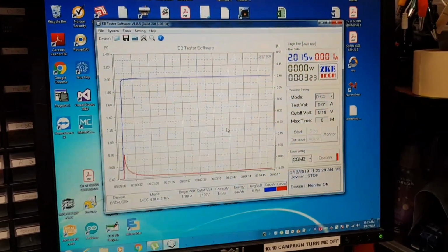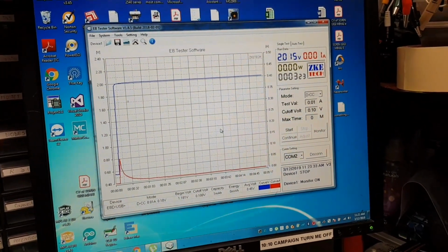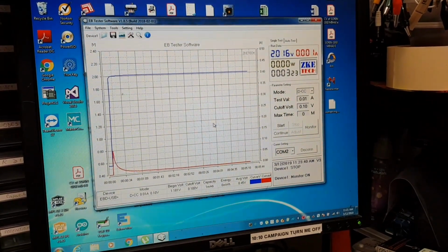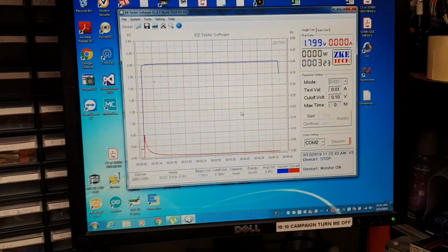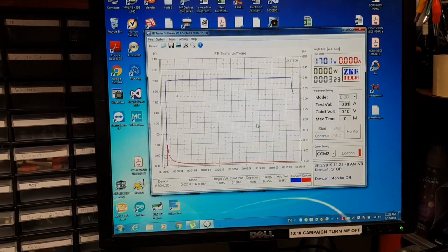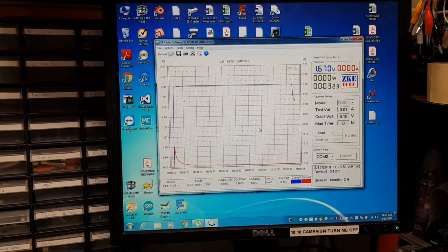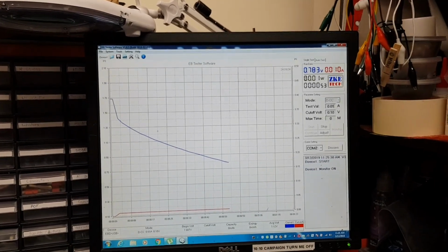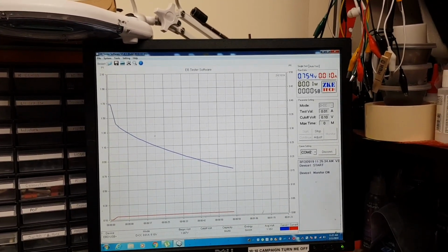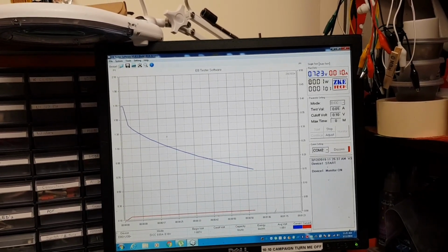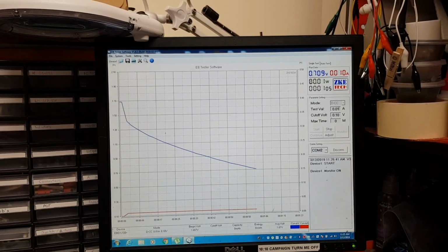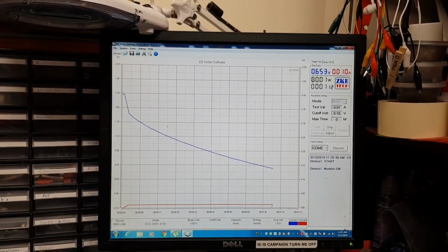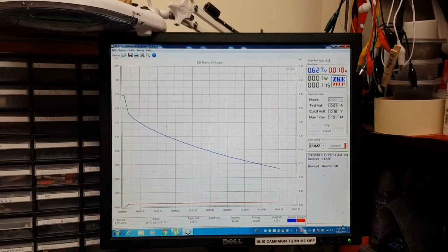Yeah, I'm going to stop now the power source and we will see at what value the voltage will drop, and that will be the voltage from the cell, from the battery. 1.8 volts. That is not that bad. Okay, so we are now on a new discharging cycle. It has 1 minute since it's discharging. Started from almost 1.7 volts, dropped to 0.7. Not very happy, but we will see what will happen after a few cycles. I'll get back a little bit later.